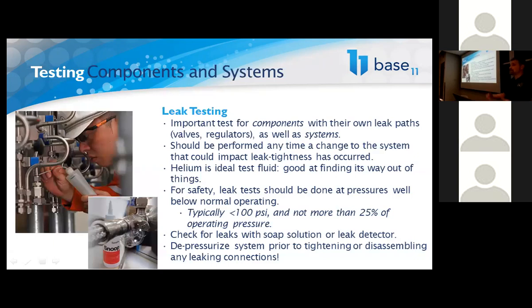When you're doing these tests, because you're using a compressed gas, obviously that stored energy poses a new hazard. So normally this kind of test is going to be done at significantly lower pressures than operating. So typically less than 100 psi, and definitely never more than about a quarter of the operating pressure. And then once you've got your system pressurized, you can use soap solution or the Snoop fluid that was talked about earlier on. You can also get helium leak detectors that will come with a little probe that you can hold next to a joint.